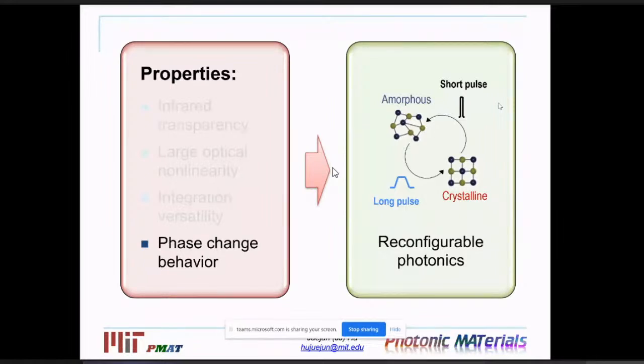And then in terms of duration, the short pulse has to be short enough, or at least the trailing edge has to decay fast enough, so that you don't induce crystallization again during the cooling process. And for that, it depends a bit on the crystallization speed. For something like GSST, cooling on the order of microseconds is actually enough, so it's a bit more relaxed. If you're dealing with conventional GST material, you will have to do it on the order of 100 nanoseconds. That gets a bit more challenging in terms of thermal design of the heater.